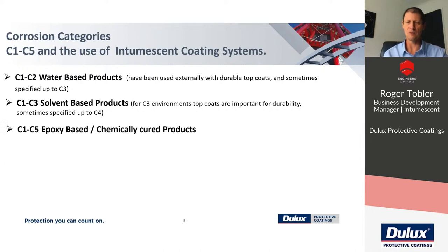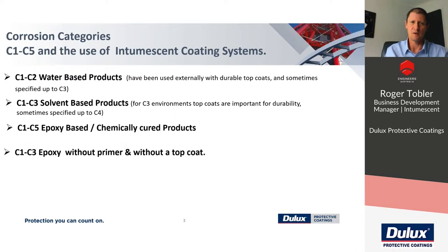And then the most durable of all, epoxies. They are intumescent coatings that are chemically cured. Epoxies really handle exposure to the environment, and they're really durable coatings. You'll find that an epoxy intumescent can be used without a top coat and without a primer. They can be applied directly to blasted steel for a C1 to C3 environment. And that eliminates a lot of additional time and cost associated with applying those additional coatings.